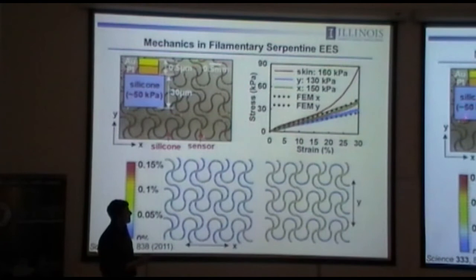In this case, the silicone substrate is very thin, about 30 microns, very low in modulus. If you get all the mechanics right, guided by theory, you end up with stress strain curves in this integrated circuit that are almost perfectly matched to the skin. So the skin is here. This is pig skin. It's pretty similar to human skin.